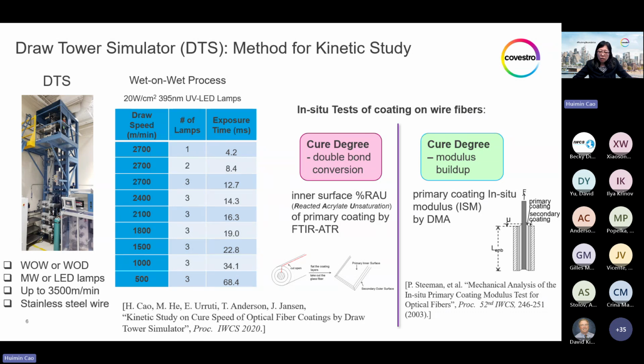And we measure the cure degree from the double bond conversion at the inner surface of the primary coating, represented by percent RAU, which means reacted acrylate unsaturation, as well as primary in situ modulus, we call it primary ISM, in situ modulus, and it's described in more detail in our 2003 paper, which you can take reference to.